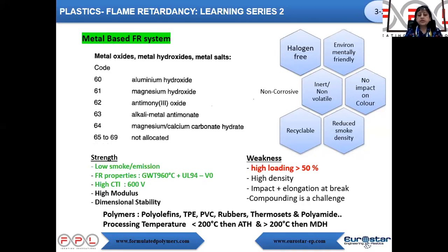So if we look at the strength of these systems, then there is very low smoke emission. The FR properties like the glow wire is 960 degrees, and UL rating we can achieve up to V0. Very high CTI values of around 600 volts. Mechanicals are also very good, very high modulus, and dimensional stability also is its strength. Now, when we come to the weakness, then it requires a very high loading. More than 50% loading is required of these metal hydroxides. So it's high density, so part weight is also higher in this particular case. It impacts the elongation because of the high loading, and of course, compounding is a challenge.